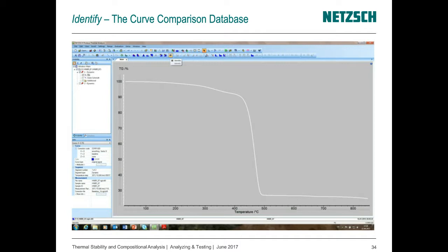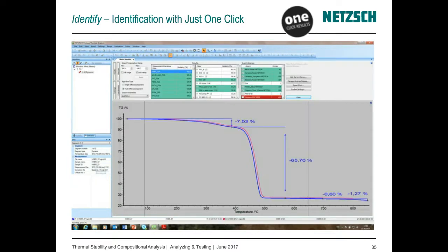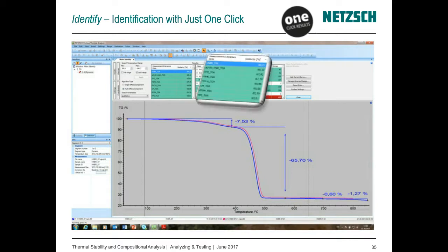And then we get something which perhaps we know already from spectroscopic instruments like FTIR. We can make a library search. The experimental curve will be compared with curves already stored in libraries. And then we can get a result as what we see here, for example. We get a similarity of more than 98% for the HNBR curve, which is stored already in the library. The blue curve on the graphic is the experimental one, and the pink one is the library curve. And just by looking at it we see that they are very similar.